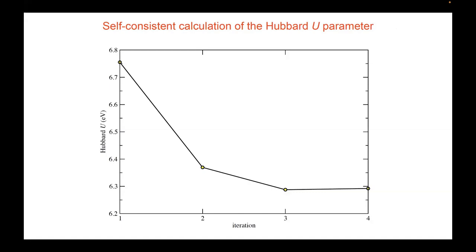There's a question that was signaled for discussion. Is the Hubbard correction compatible physically and numerically with the calculation of XPS and XAS spectra? Yes, we actually use the XSpectra code of Quantum ESPRESSO together with DFT plus U and plus U plus V. And the agreement with experiments was not too bad. But we concluded that the global value of U was not good enough because it shifted the empty states too much.